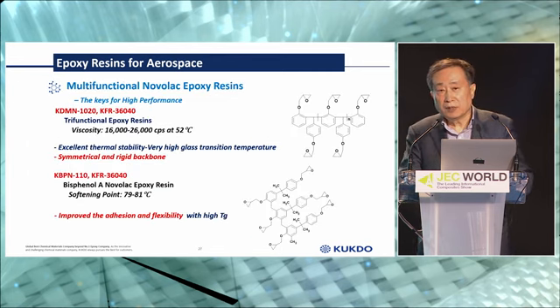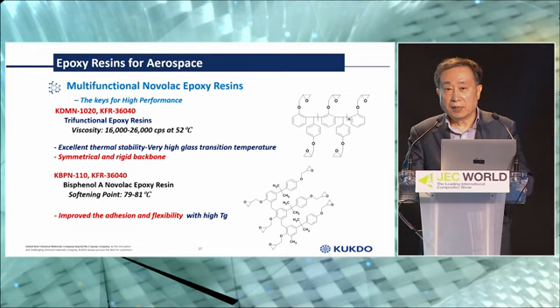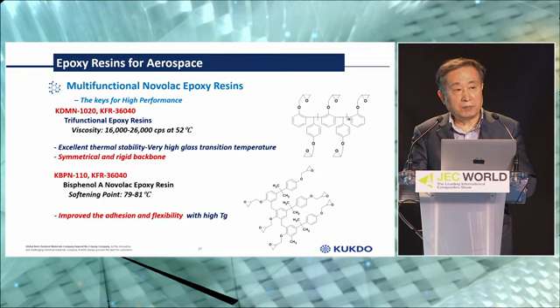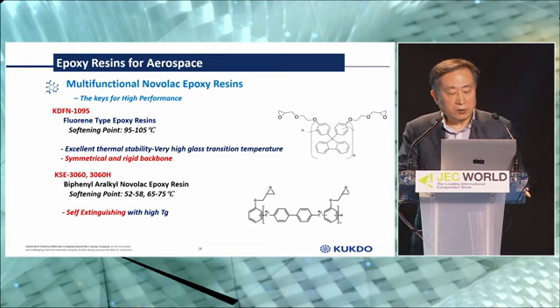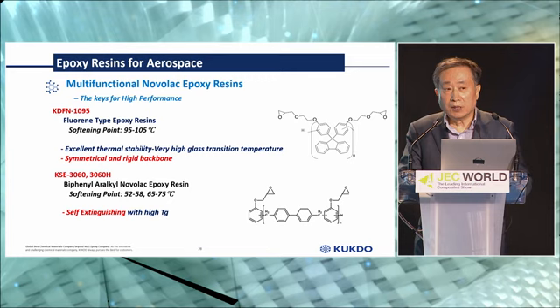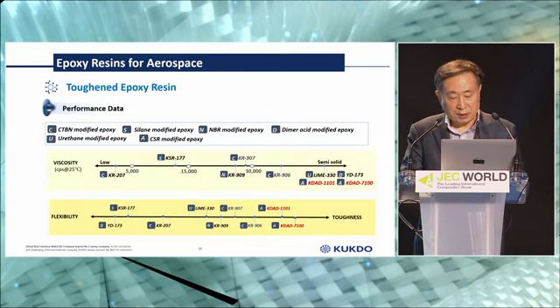And also we are developing and supplying the market multifunctional novolac resins, mostly for heat resistance and high mechanical properties. So bisphenol A novolac epoxies or bisphenol F-based novolac epoxies, multifunctional, you can easily have more than 200 degrees Celsius of heat resistance, high Tg purpose. And this is the multifunctional novolac system. We are manufacturing this novolac resin for our internal captive use. So we can design many different types of novolac resin, like multifunctional or BPA novolac, this kind of thing.